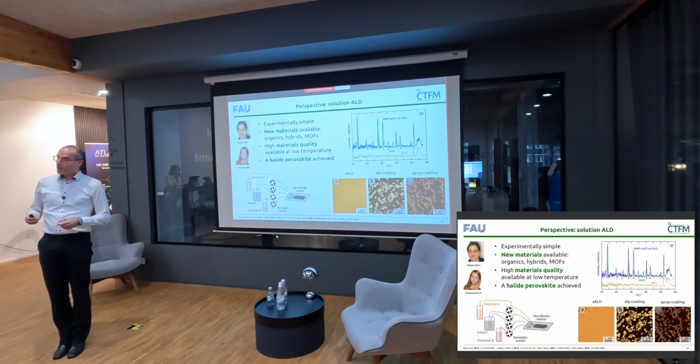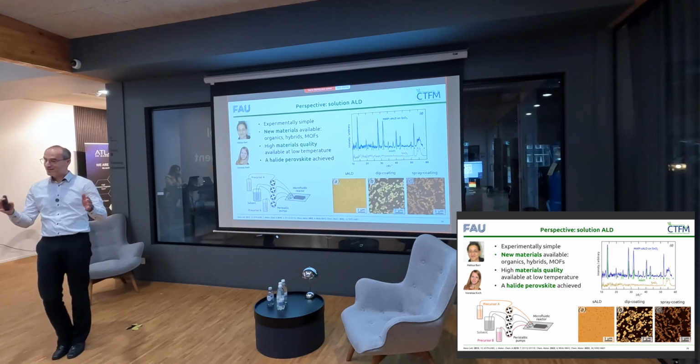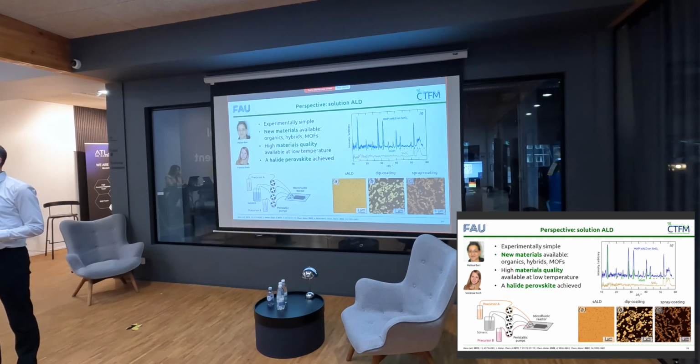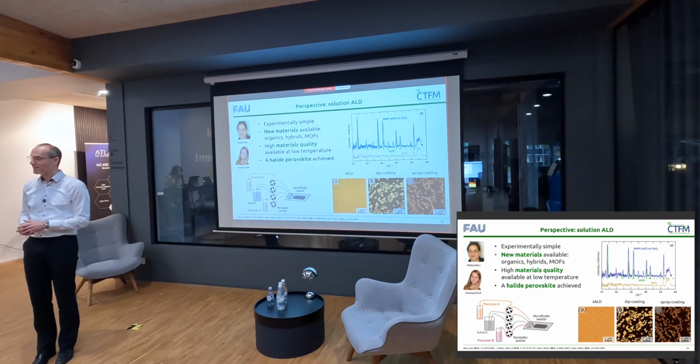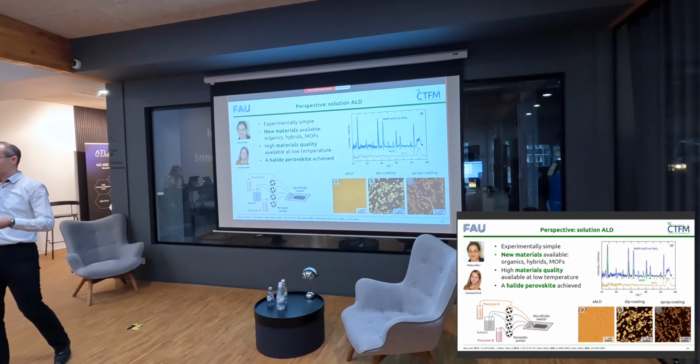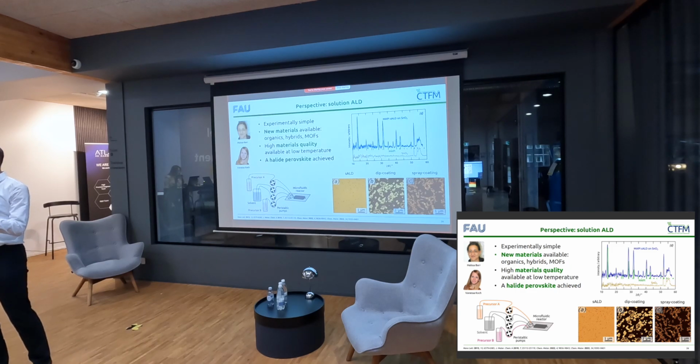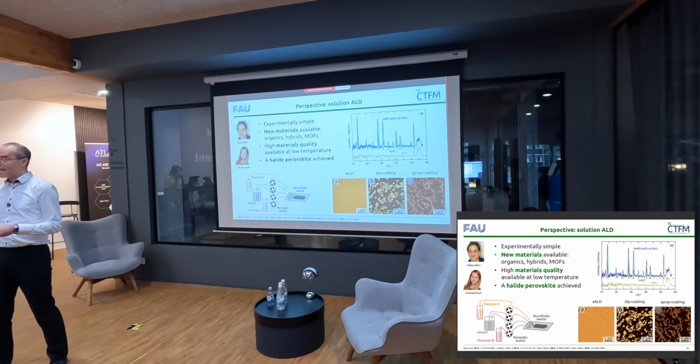Where are we going? There are some limitations of ALD, even though I love it. One of the limitations is the materials. Not everything is metal oxides, and ALD is very good for metal oxides and some sulfides and nitrides, but there's a whole world beyond that, and this world contains things like silicon, elements that are really hard to reach by ALD, like organics, hybrids, metal organic frameworks, and ionic solids. And ions is certainly not something that you will be able to just evaporate.